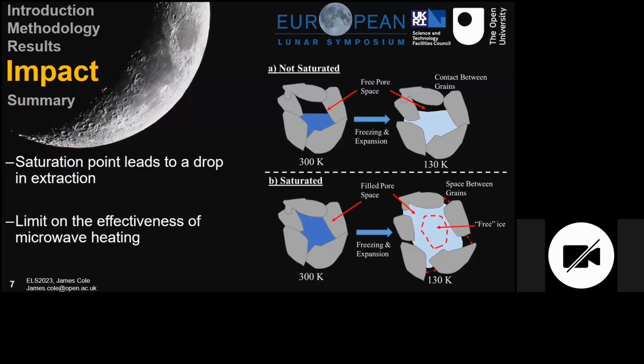So when it expands, you get the grains pushing apart. That reduces the contact area. And possibly more importantly, you get these regions of free ice forming. The water ice really doesn't interact with the microwaves at all, and therefore these regions of free ice can actually be maintained. And therefore, that's why you get this drop off in extraction. Overall, this suggests that microwave heating might be better suited to low to medium ice deposits on the lunar surface.